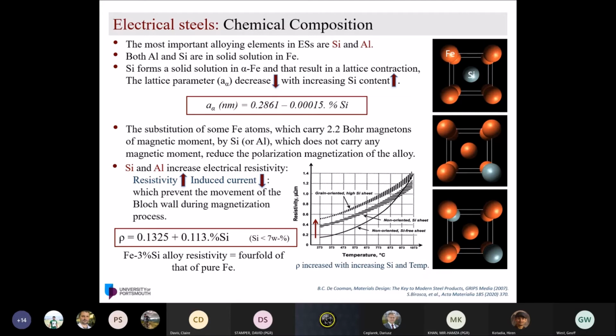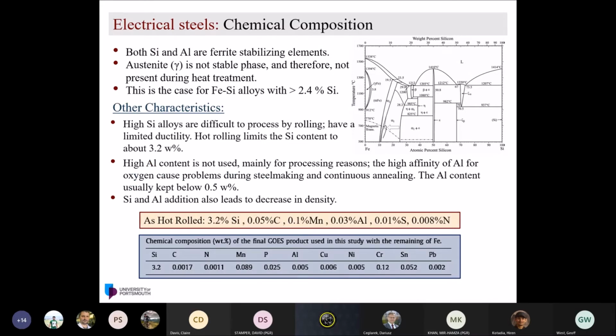So next, if it is possible to put more silicon, why don't you put a lot of silicon and aluminum? The reason is very simple: silicon and aluminum, if you put them in steel, make the material brittle, and that causes a lot of difficulty during hot rolling and cold rolling, because the alloy is so brittle it will crack during the thermomechanical processing. That's why we restrict the silicon to around 3.2, 3.3, not more than that. Otherwise, we cannot process it because it will be very hard.